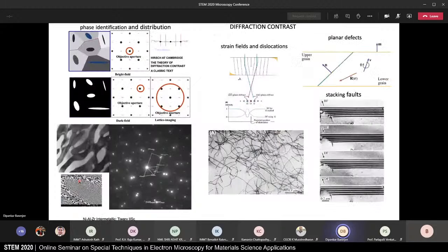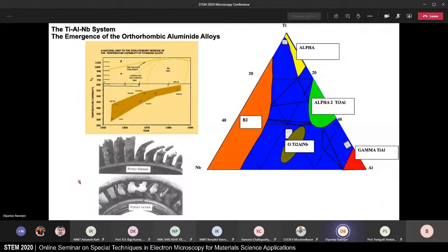In its basic form, TEM relies on diffraction contrast. So you can do phase identification and distribution by putting a physical aperture on the transmitted beam or any one of the diffracted beams, and you can identify which phase has which crystal structure and so on, and the distribution of phases. You can use strain fields in the sample associated with defects, which affect local diffraction, to image defects such as dislocations, or the displacement associated with planar defects such as stacking faults, in terms of the very characteristic fringe contrast.